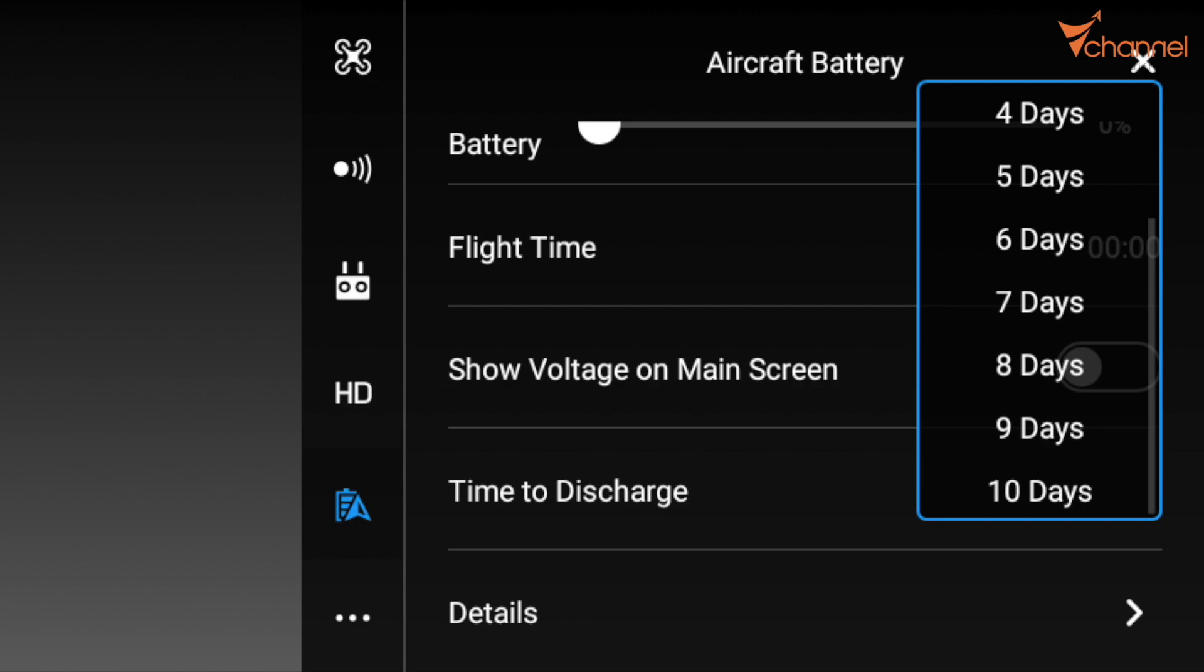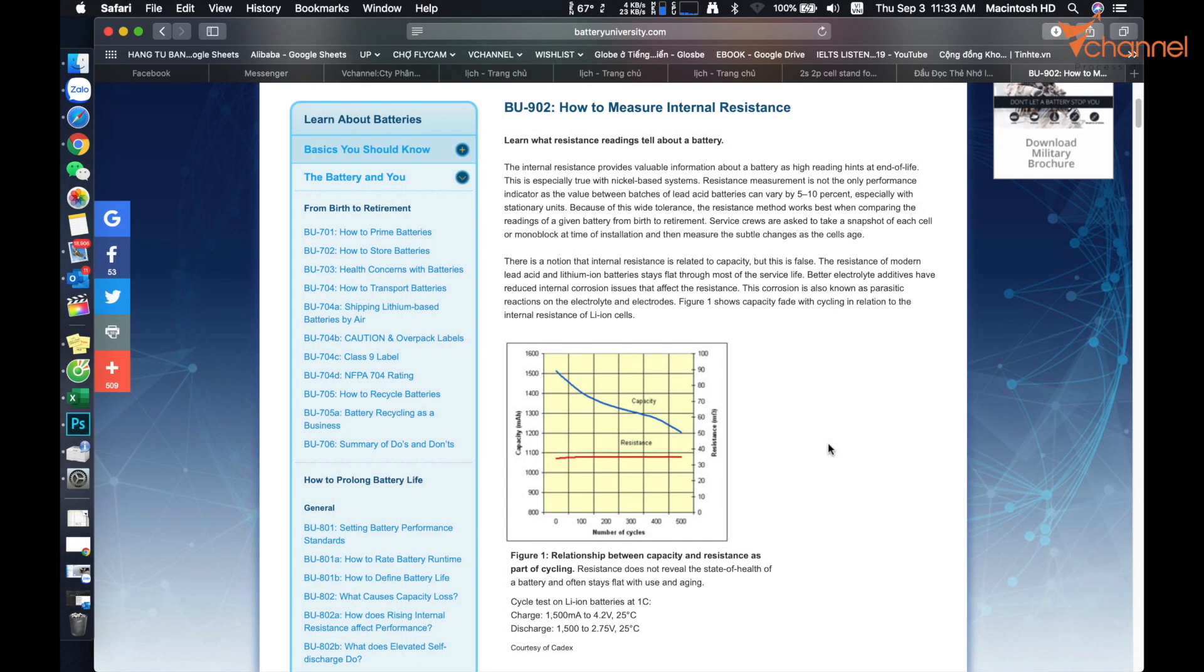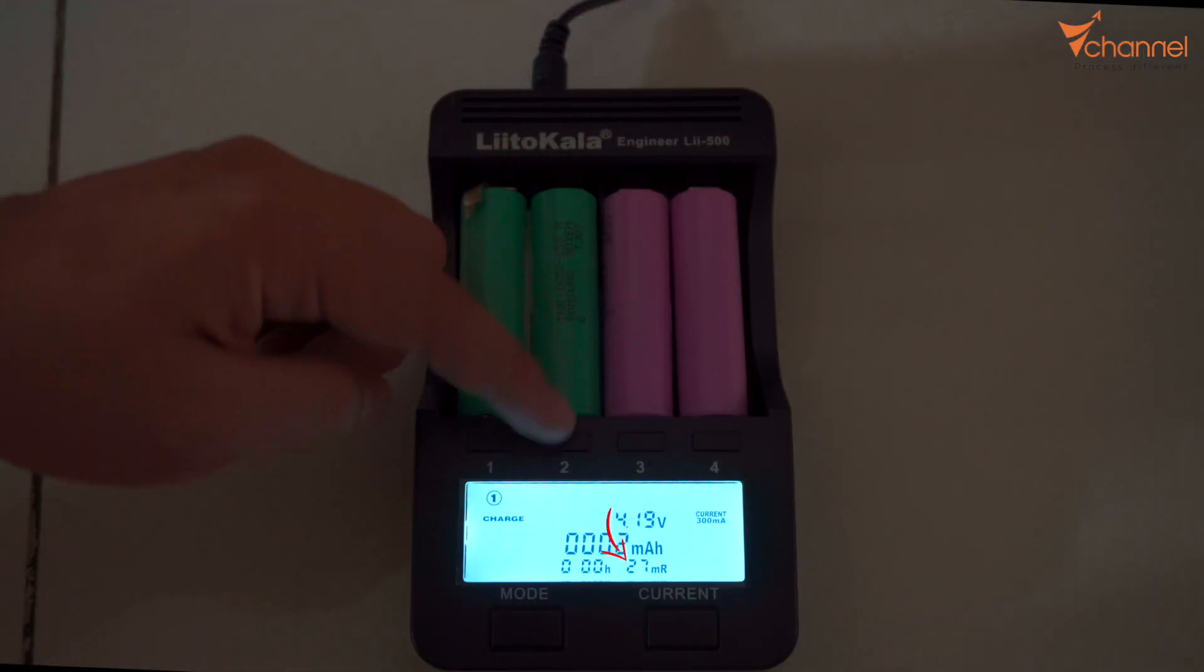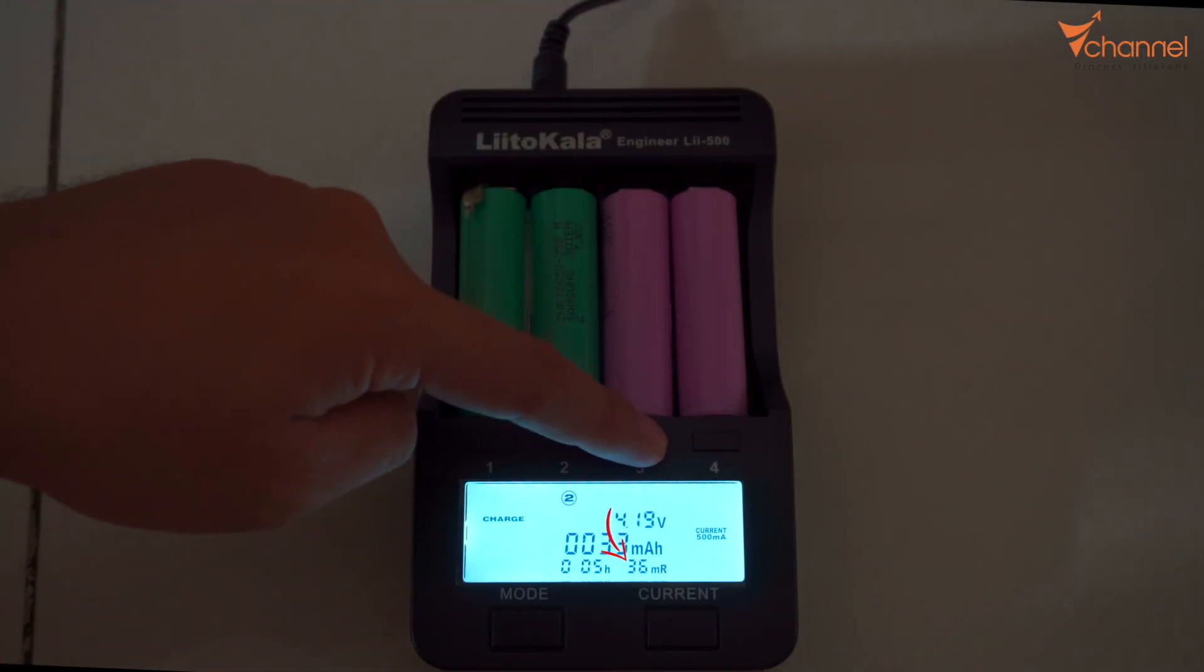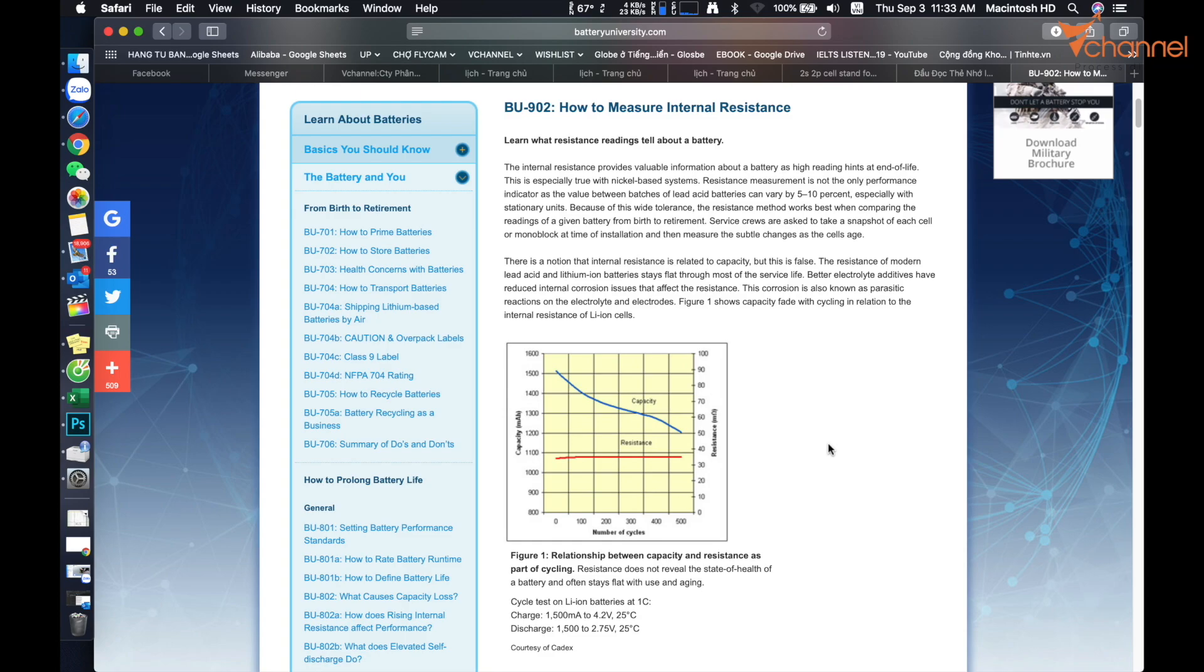Next is the element to evaluate battery health, which is internal resistance. To calculate the internal resistance, you can use the formula. The new charger generation has shown the internal resistance already, like this, right on the screen. The lower internal resistance, the more battery health. Under 50 milliohms, the battery is nearly new. From 50 to 100 milliohms, the battery health just remains about 80%. If it's over 200 milliohms, we should not use anymore. It's very bad, can decrease voltage suddenly and even burn.